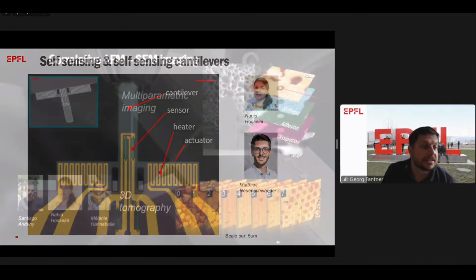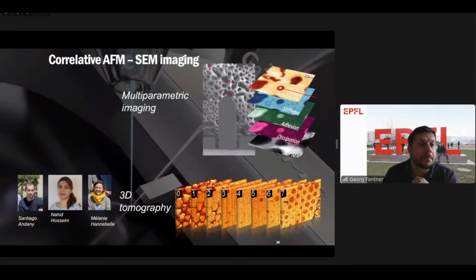So here are just some examples of experiments that we've done. Here, there is a healable polymer sample that we're imaging, and we're getting the SEM image, but we're also getting the mechanical topography from the AFM, the stiffness, adhesion, and the dissipation. This is really exciting for us because now we can not only look at the structure, but also the function of the materials. Because we have this integrated not just in an electron microscope, but actually in a dual beam, we also have the focused ion beam. We can use the AFM to image and the focused ion beam to slice the sample, and then we can image at the same spot. We can image multiple slices, and then we can do a 3D tomography through the sample, but with AFM contrast.